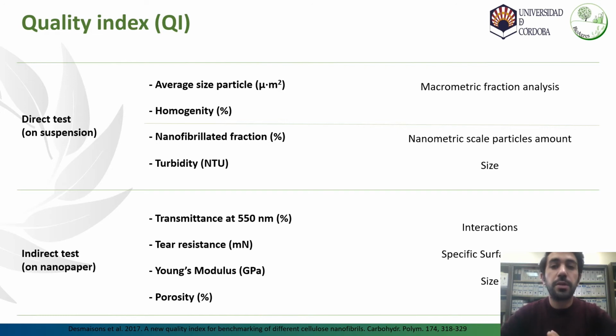From the observation under the optical microscope, it was possible to characterize the macrometric fraction by analyzing the average particle size and the homogeneity of the sample. Therefore, the higher the nanofibrillation, the smaller the mean particle size, and in most cases, the greater the homogeneity of the suspension. The nanometric fraction was analyzed by 2 direct tests on the suspension, by measuring, in one case, the nanofibrillation fraction, a kind of nanofibrillation yield, by centrifugation of the suspension, and by measuring the turbidity. The lower the turbidity, the higher the nanofibrillation in this case. The indirect tests give information on the interaction of the nanofibrils, their surface area, their morphology, as well as other relevant information.